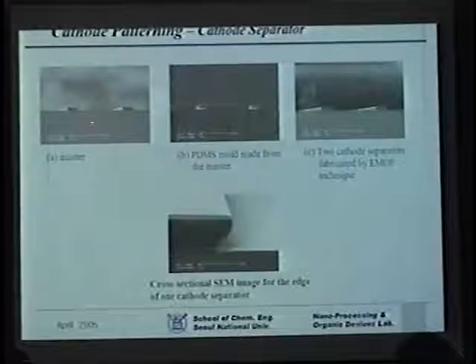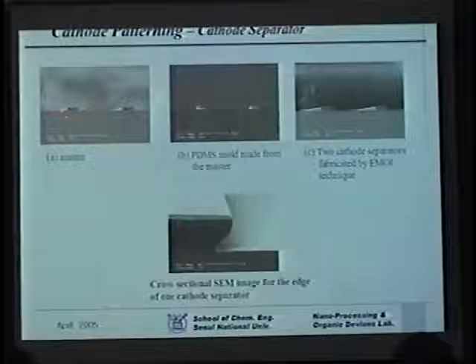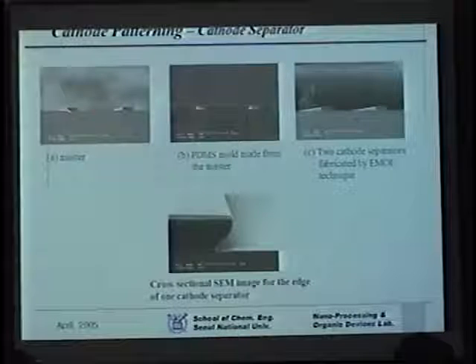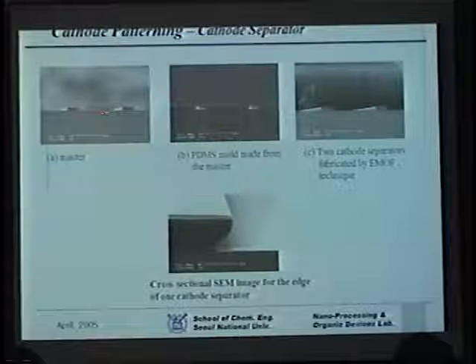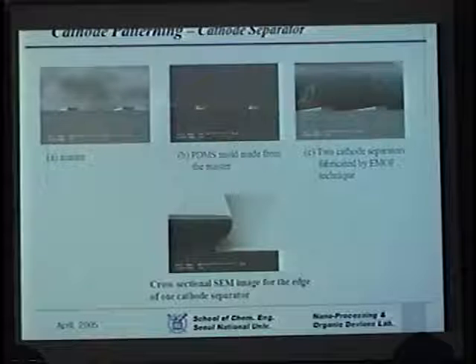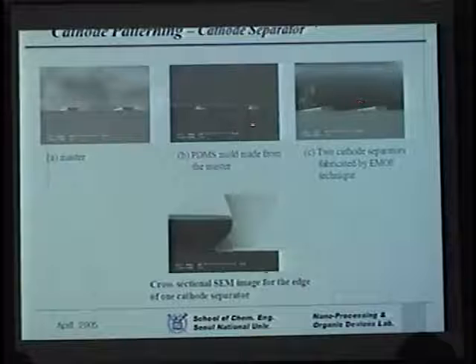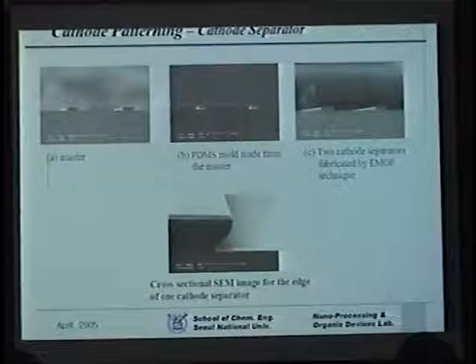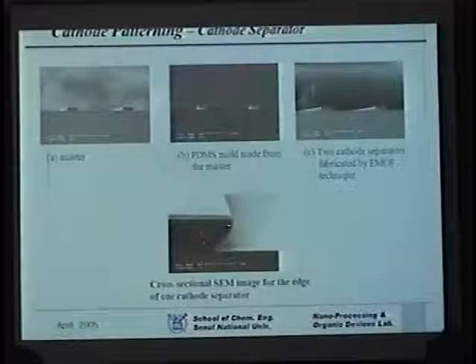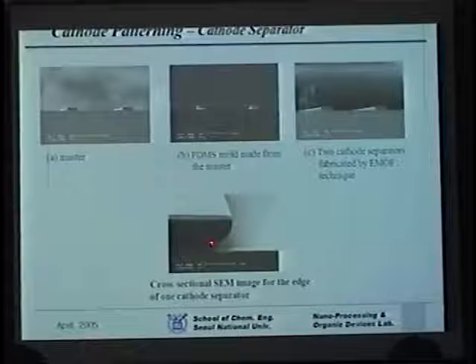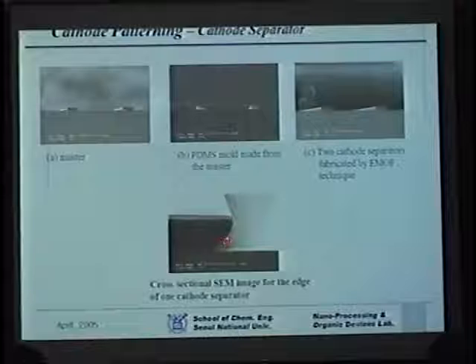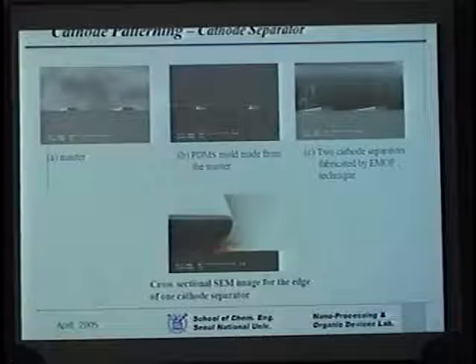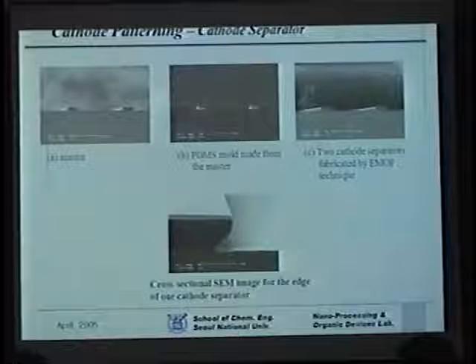So here's a typical example, or the actual results. This is the master. This is the mold made from this master. This is the cathode separator made with the use of this master. Now, upon magnifying the edge of this cathode separator, you can see that there's enough clearance between this edge and that to give you good separation between adjacent devices.